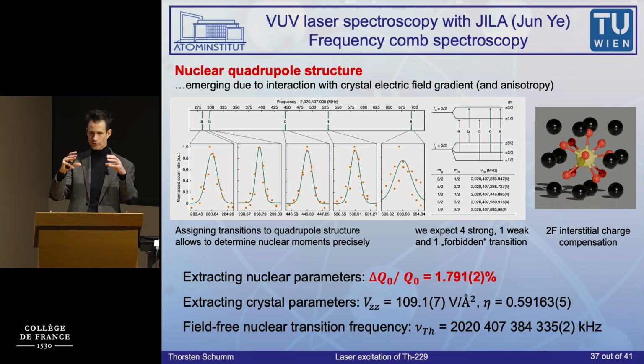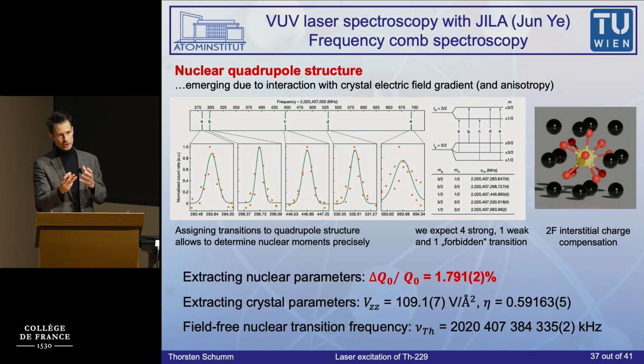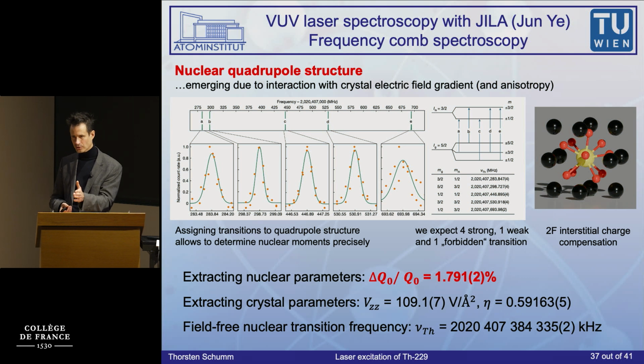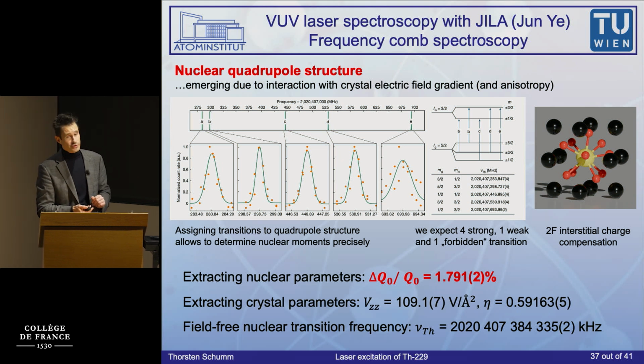And that means the proton distribution is not spherically symmetric, which leads to an electric quadrupole moment. That electric quadrupole interacts with an electric field gradient of the surrounding crystal, and that means the ground state, this is the nuclear ground state, this is the nuclear excited state, there is a quadrupole splitting. That's a known effect in nuclear physics. Due to the interaction with the crystal matrix fields, the ground state splits into 3 levels, the excited state splits into 2 levels, which makes 6 possible transitions. One of them is forbidden. The 5/2 to 1/2 one here is forbidden. The others are observed. And that explains the lines we have seen.